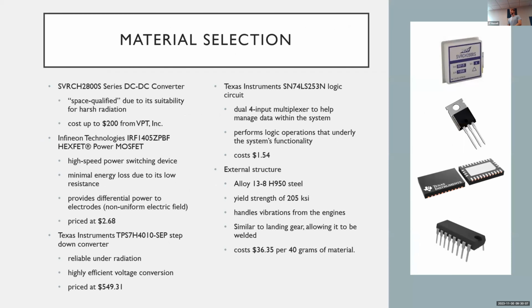Okay, so for the material selection of our EDS, we had 5 main components, including the external structure. Our first one was our series DC-DC converter, which is space qualified due to its suitability for harsh radiation. If you look in the top right, that's a picture of the VPT DC-DC converter. And then for our second material, we had a MOSFET, which is a high-speed power switching device. It has minimal energy loss due to its low resistance and also provides differential power to electrodes to help create a non-uniform electric field. That is also shown on the right, the second one from the top.